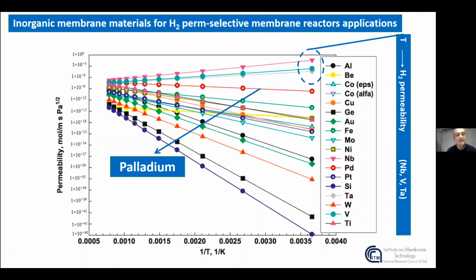Now, looking at this graph in which the hydrogen permeability versus the reverse of temperature is plotted for several inorganic membrane materials useful for hydrogen perm-selective membrane preparation, it's possible to observe in the upper part of the graph the metals niobium, vanadium, and tantalum possessing the highest values of hydrogen permeability with respect to the other metals. Furthermore, the permeability of hydrogen for these three metals decreases by decreasing the temperature, and this is a fantastic behavior.